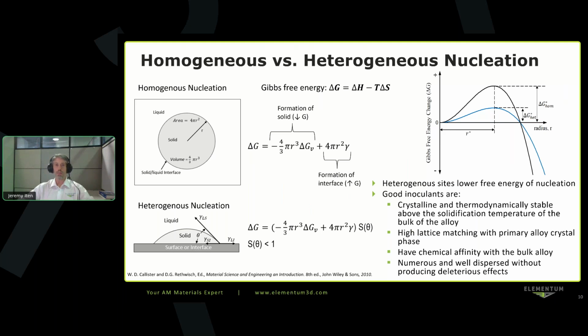So you have a minimum size of a stable nucleus that you need. If you're below that size, your surface area is too high and it's unfavorable. If you're above that, then the volume energy dominates and it's favorable. So this is some of the things that you need to consider when you're looking at the right nucleation sites to introduce, how you go about that, and what sizes will work and what won't work.